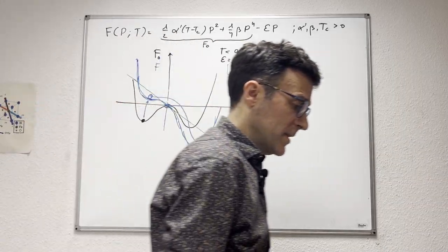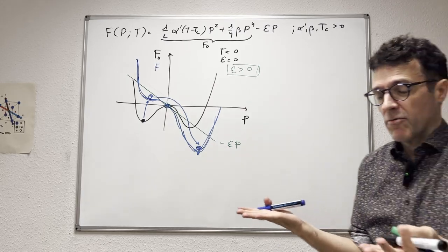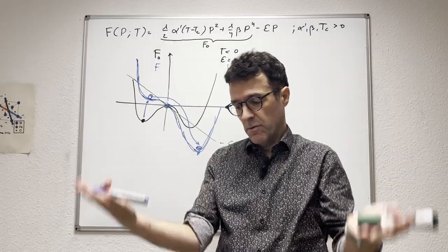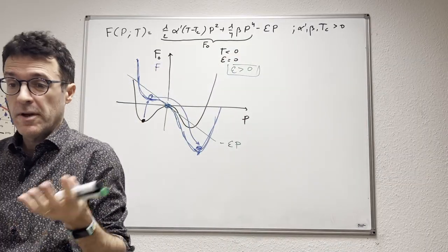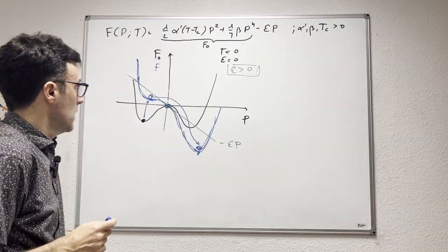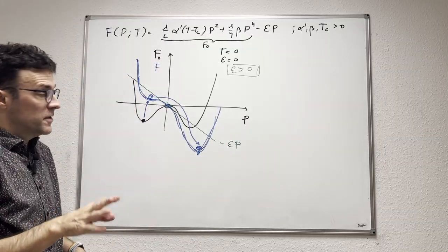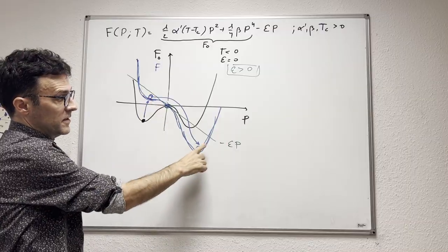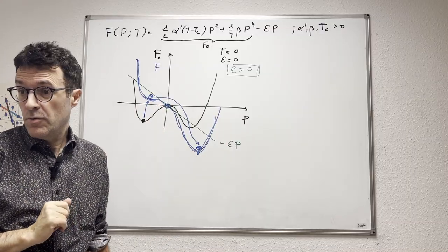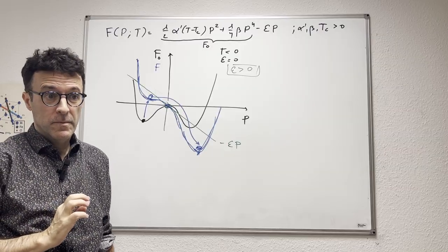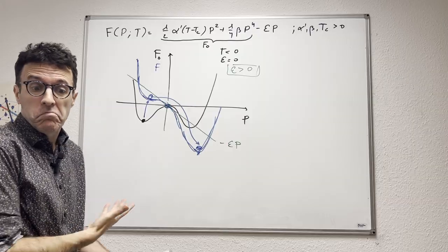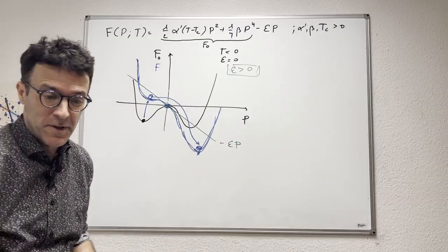Okay? So in a very simple graphical way, this is what ferroelectric switching is, and obviously it is captured by our Landau potential. All that we need is two minima that are equivalent in the absence of field, and whose relative stability can be played with when we apply an electric field. It's as simple as that. Also, you will see it mathematically in a moment, but if the field is large enough, positively large enough, this minimum we can make disappear altogether. All right? Okay, so this is the basic thing that our theory has to capture.